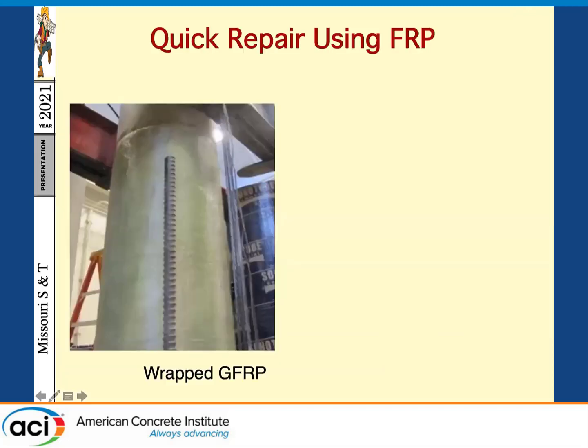Now, after we tested the first set of columns, MoDOT, Missouri Department of Transportation, was curious about how we can repair this after an earthquake. So what we proposed for them is a rapid repair technique that consists of, first, we clean the column. I'm not sure if it's clear over here, but this is a hollow core column that was tested first in the first phase. After that, it had some rupture on the FRP tube, and we went back and cleaned the column, removing any big chunks of concrete that were loose after the test.